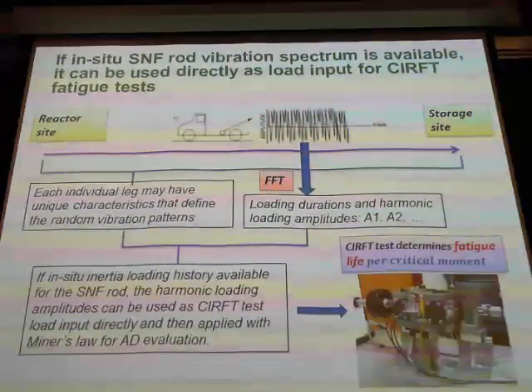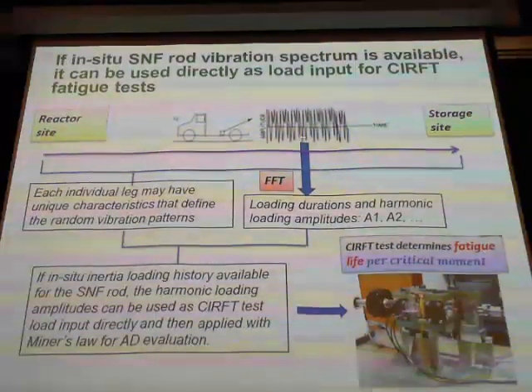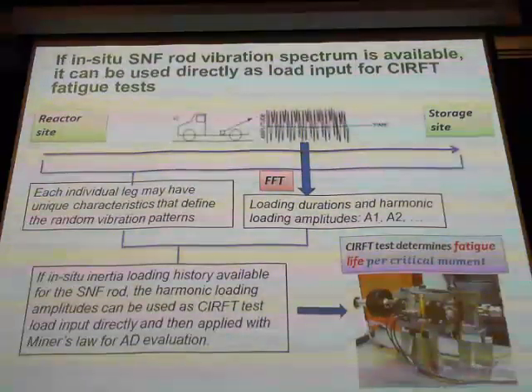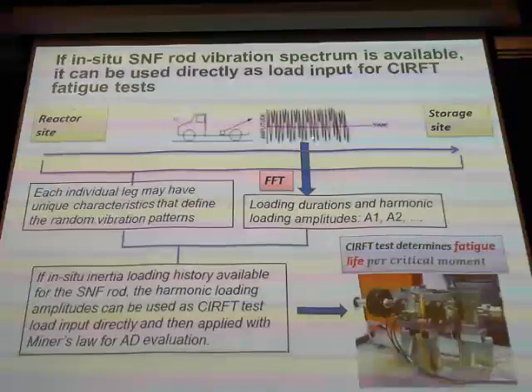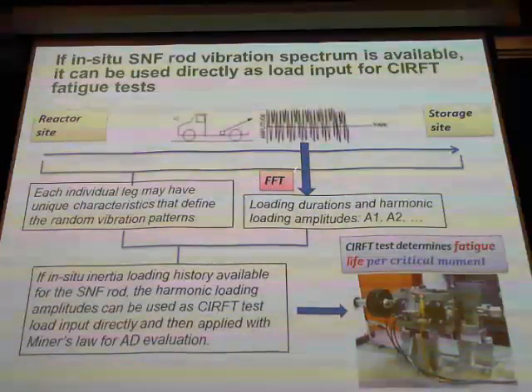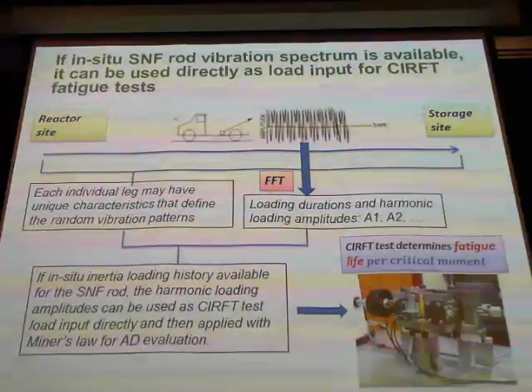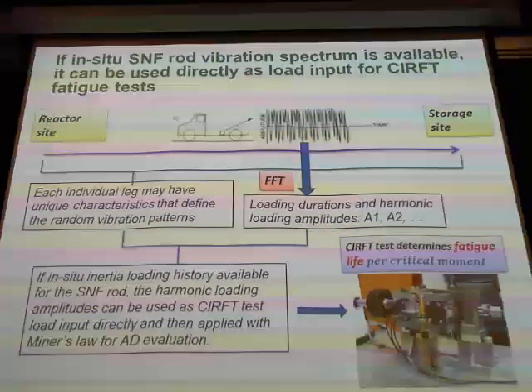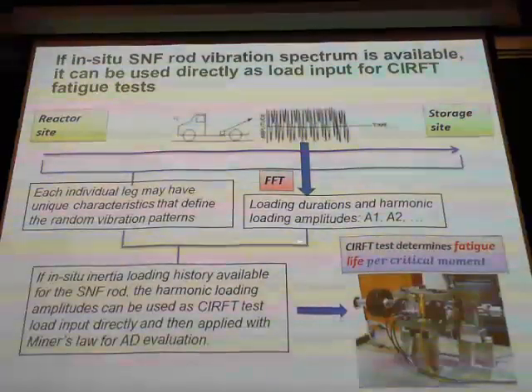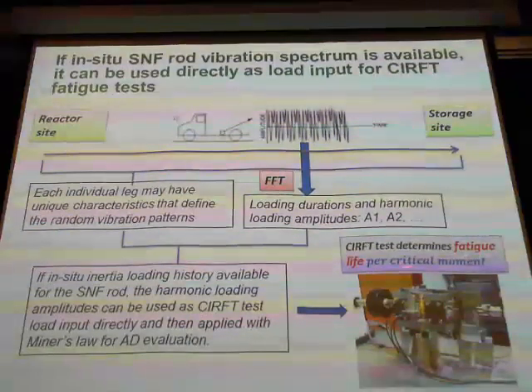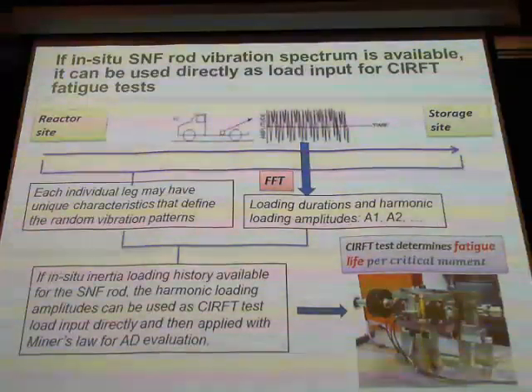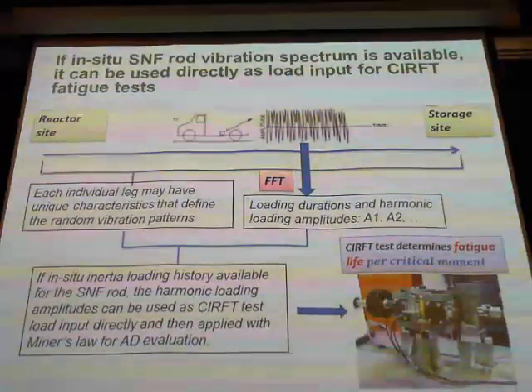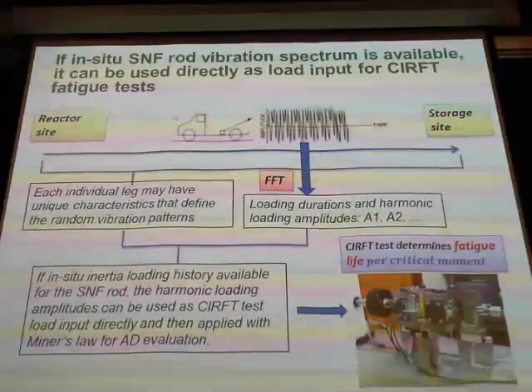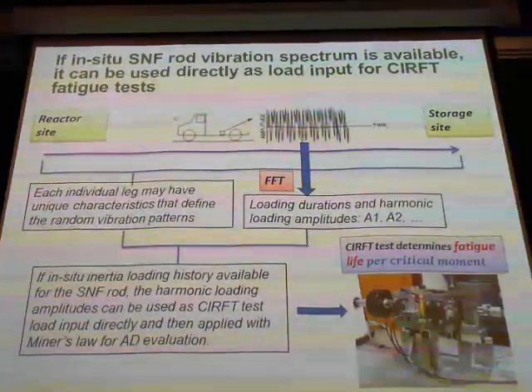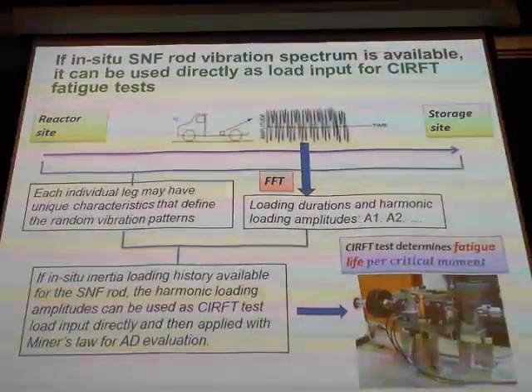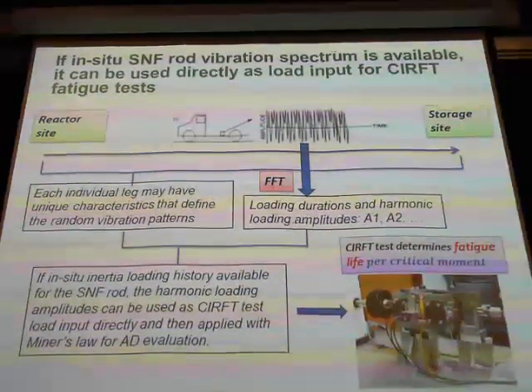So it's important. I break this problem into a so-called achievable problem. You have random vibration, and you do a fast Fourier transformation into isolated harmonic waveforms. Each one has an amplitude and duration. Then the device I generate can cycle under this loading, and I see how many times I break the sample. So you know at this frequency, at this target loading, how long the cycle life is. So basically, accordingly, you can generate your fatigue prediction.